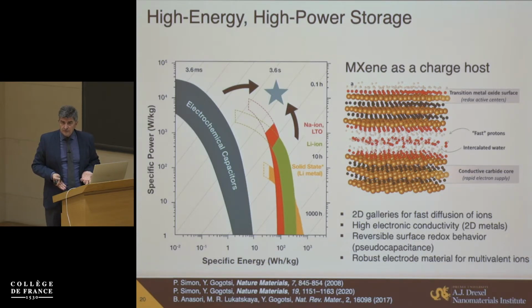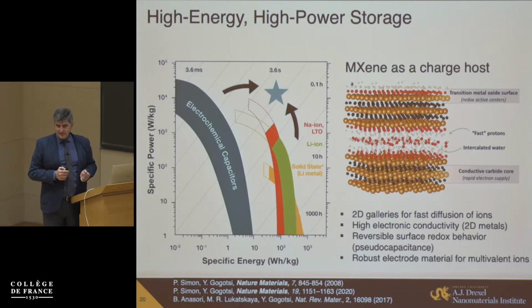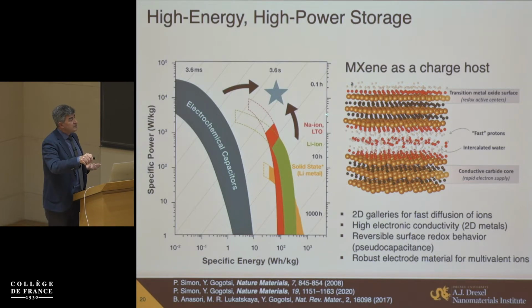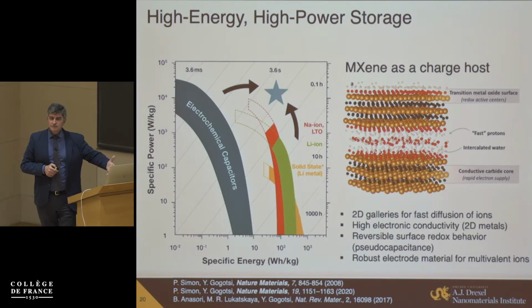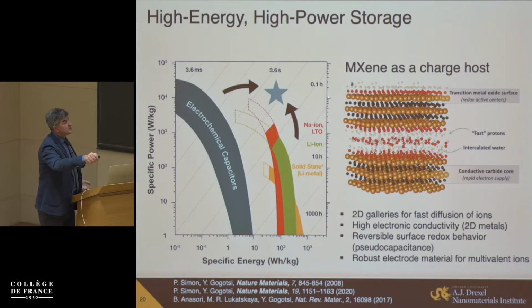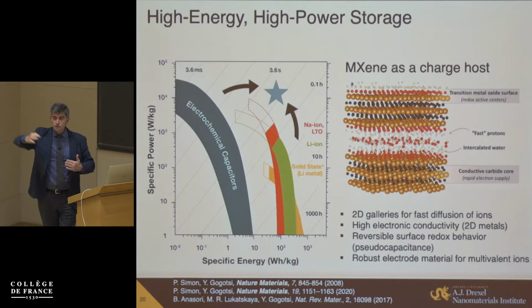If you run high current and your material has poor conductivity, it will simply end up with Joule heating, and consequences of this are very well known. So what I believe we really will need to make it there in terms of power, we need materials that have both ionic conductivity, on the surface conductivity, basically nanomaterials to a certain extent, and electronic conductivity, which allows you to deliver electrons to the side also through thick electrodes, not only here.